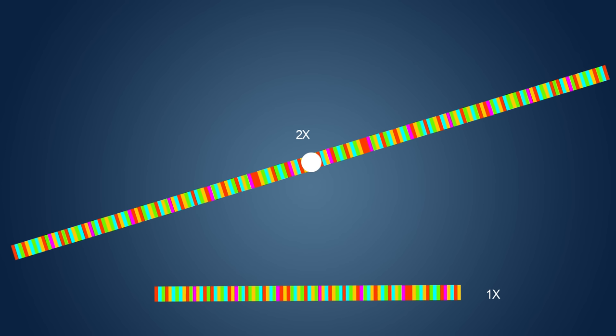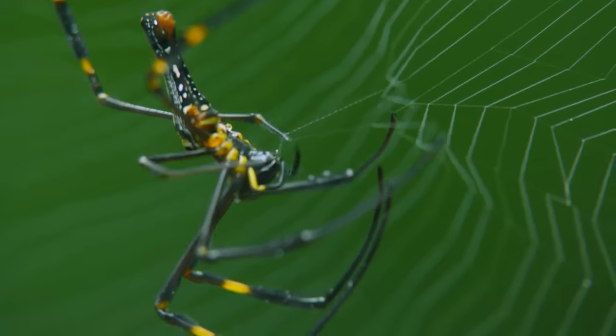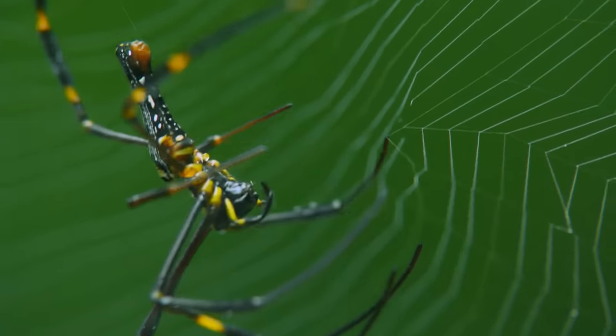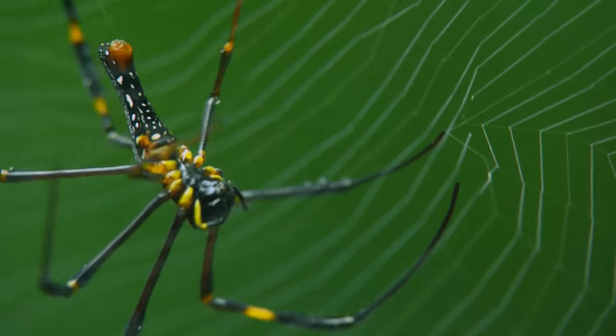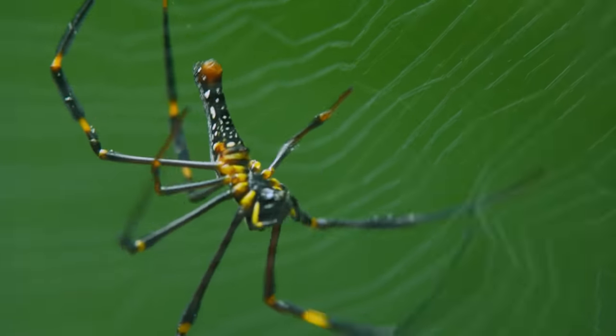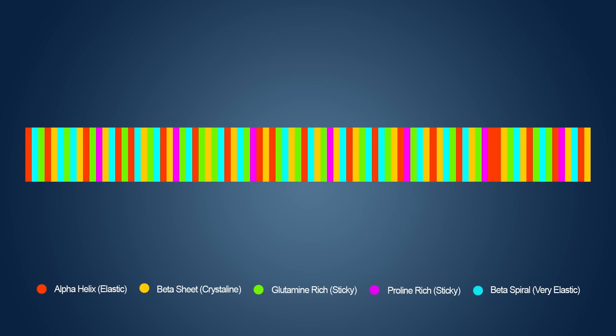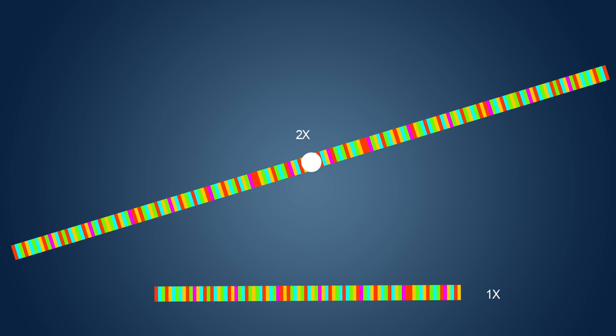But even without mineralizing, this should actually make the individual protein filaments stick together at their ends when calcium is present. This sort of artificially extends the length of an individual fiber by linking two together. One of the reasons natural silk is so strong is because the protein itself is actually really long, about 3,000 amino acids total. My protein is only about a third of that, so these mineralization peptides are one way of sort of cheating a longer protein into existence by binding two shorter ones together end to end.